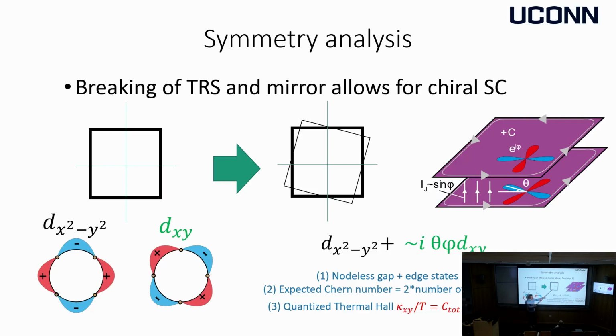Now let's twist. If I look at this picture, it doesn't have those mirror symmetries any longer, which means that those two order parameters are no longer distinct, and they're allowed to mix. But since I have time reversal symmetry, I'm not allowed to make any complex phase difference between the two, and that's what the current does for me. Once I apply current or any other time reversal breaking perturbation, I can mix d-wave superconductivity, x squared minus y squared and dxy, with a complex phase in between. And this kind of order parameter is well known to be a topological superconductor with a Chern number of 2 per layer.